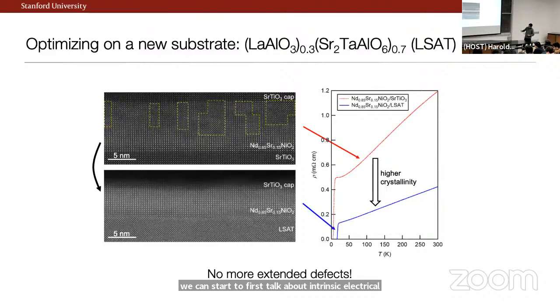And kind of not a surprise, maybe, to you is that if we go from this to this, a lot of things improve. First, the scale of the electrical resistivity drops way down, right? Less of these guys to scatter off of that I was telling you about. In fact, the superconducting transition goes to higher temperature. But more importantly, we think now that this is a very reproducible measurement and it has some physical significance.